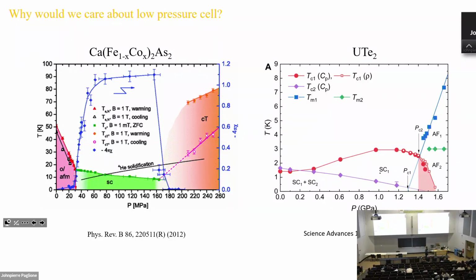Right? The pressure, we increased it too much. So we didn't even see the decrease of the TC at the beginning. So that's another example where sometimes you really need a low pressure, not high pressure. If you apply too much pressure, you miss this one. So that's one reason. Sometimes the phases are very sensitive to the pressure.